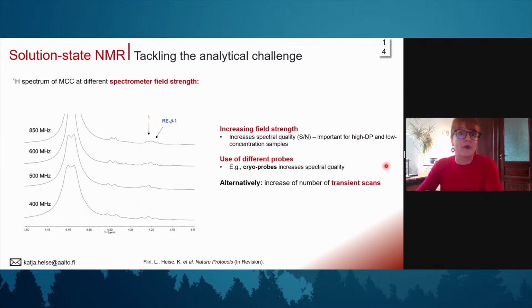Alternatively, what you can also do is use different probes. What they have tried is the use of cryoprobes, for example. And that's something that we have at Aalto, we mostly work with a 400 megahertz spectrometer, so we increase the transient scans. With the scan number, I can increase my signal to noise ratio and my spectral quality.